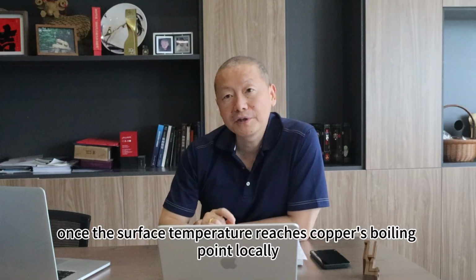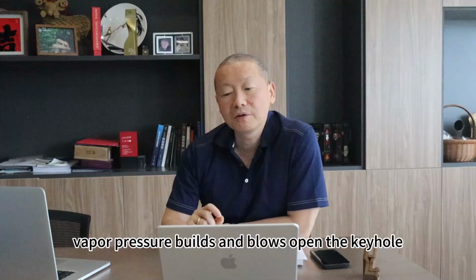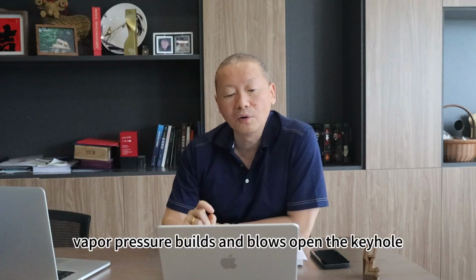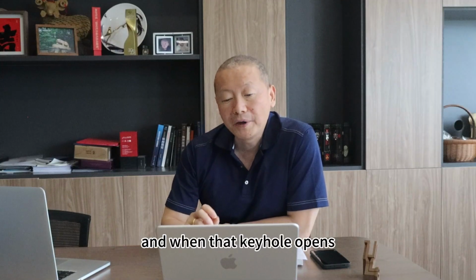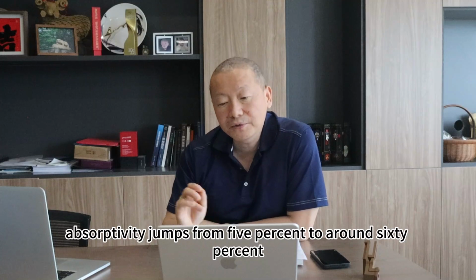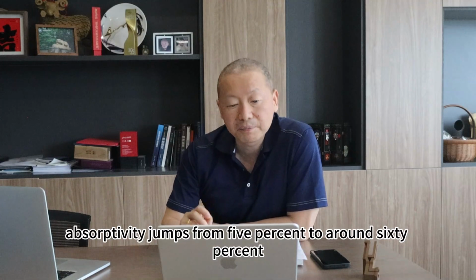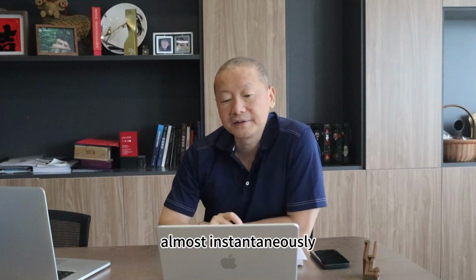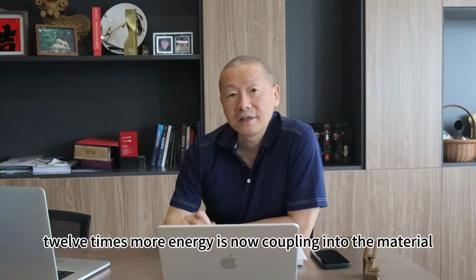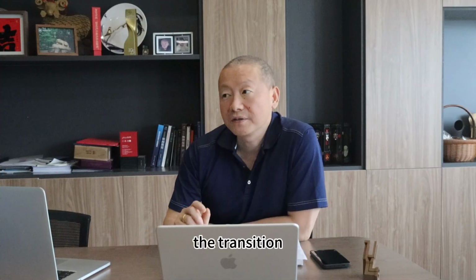Once the surface temperature reaches copper's boiling point locally, vapor pressure builds and blows open the keyhole. And when that keyhole opens, absorptivity jumps from 5% to around 60%, almost instantaneously. 12 times more energy is now coupling into the material. Welcome to phase 2, the transition.